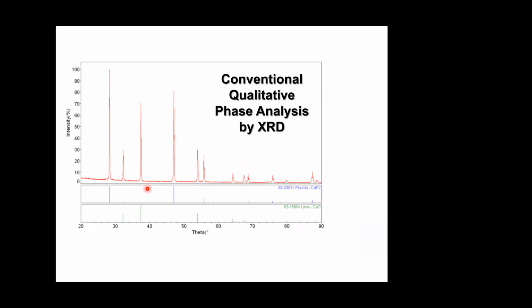If all the peaks can be explained by the standard pattern, then you know, for example in this case, the sample has crystal phase A and crystal phase B. That is the perfect use of X-ray diffraction, and that's what a lot of people do very nicely. But this is what we call the conventional qualitative X-ray diffraction analysis, because you know you have A and B. If I further ask how much A is there and how much B is there, that becomes a relatively difficult question for a lot of people to answer, because they only know A and B since they fit the peaks, knowing A is here and B is here, but how much, they don't know.